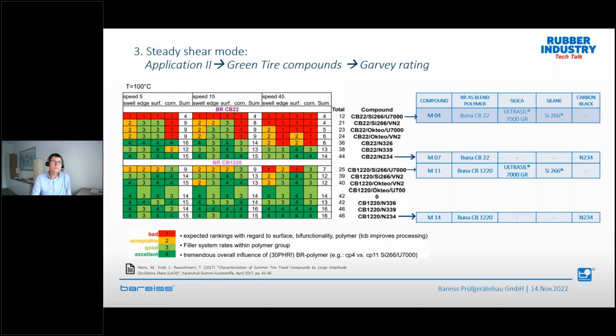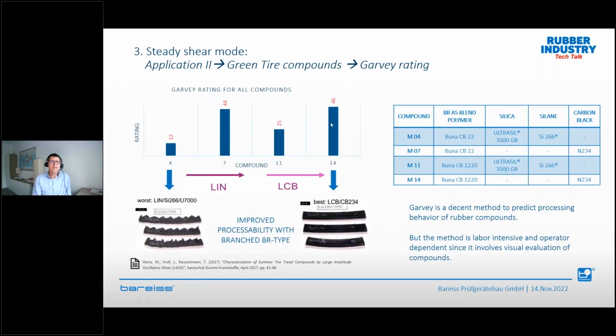So the idea was now, can we make these correlations? When we look at these 4 samples, 4, 7, 11, 14, remember 4 is the one with a linear polymer and this silica silane, and you see these very bad Garvey results. On the other side, you see 14, which has a very nice surface. But honestly, no instrument worked. We did a lot of dynamic tests, we did a lot of high pressure capillary rheometer tests, but nobody really could find a nice method.